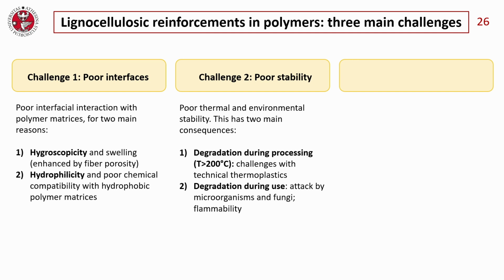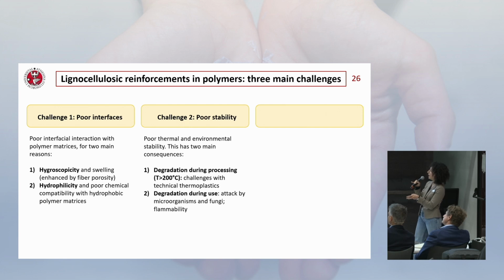So they degrade during processing above 200 degrees, more or less. And this is challenging, especially if you want to combine them with technical thermoplastics, like polyamides, polyamide 6 or polyamide 6,6. It is not a challenge if you want to combine them with polypropylene, of course. Also, they degrade during use. They are being attacked by fungi, microorganisms, and they also show higher flammability than, for example, glass fibers.